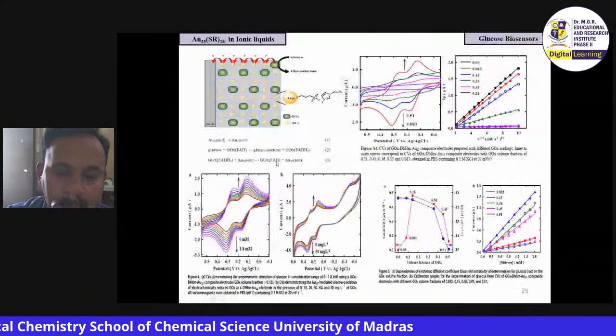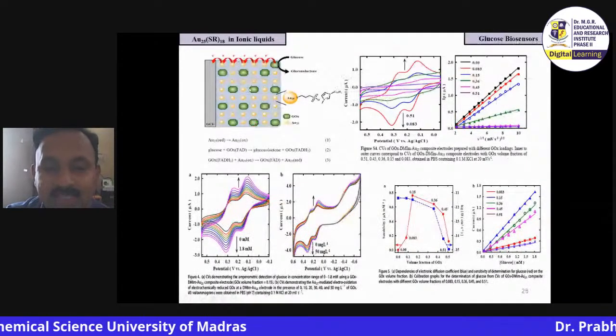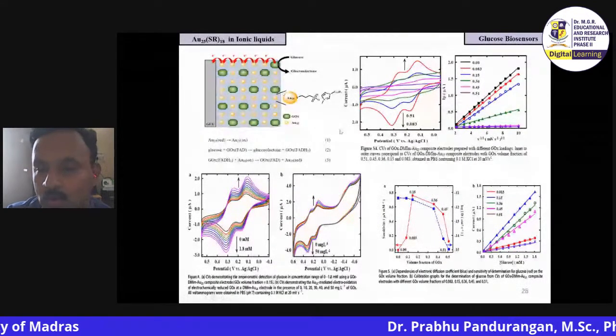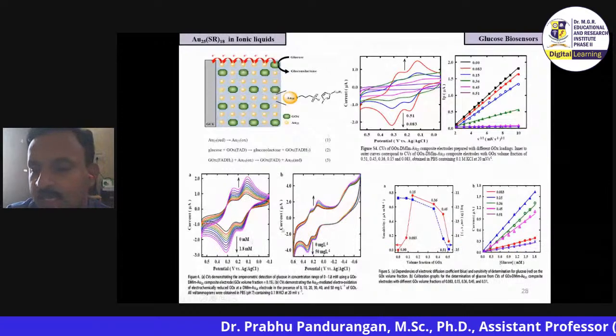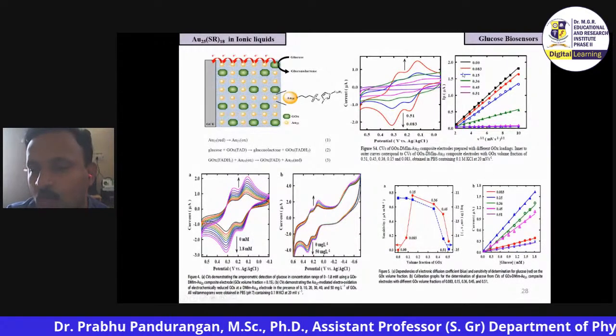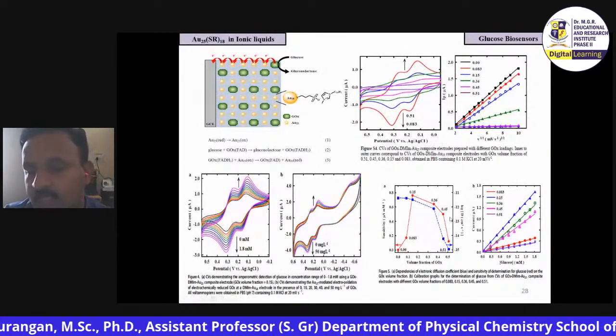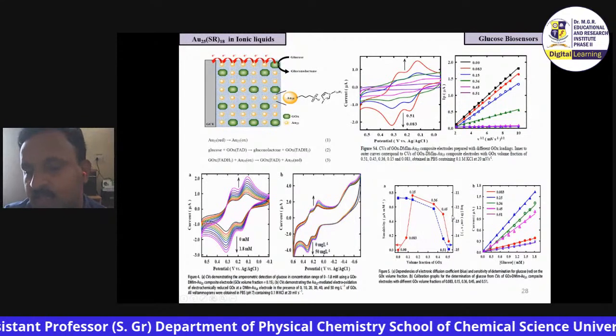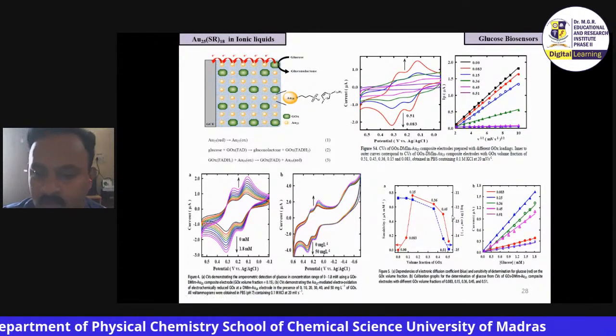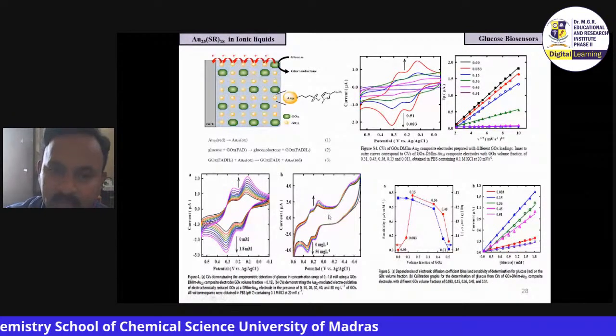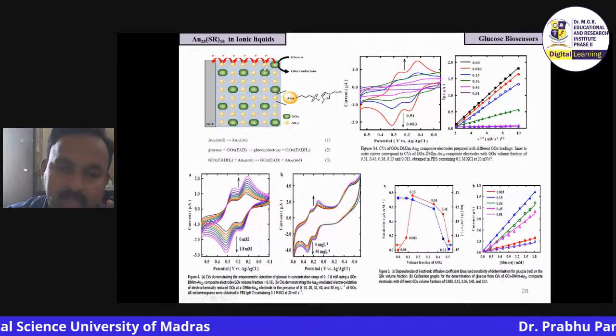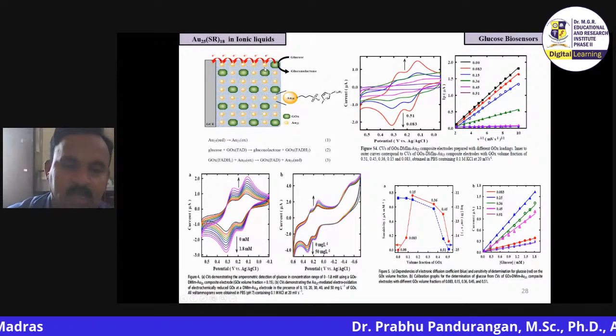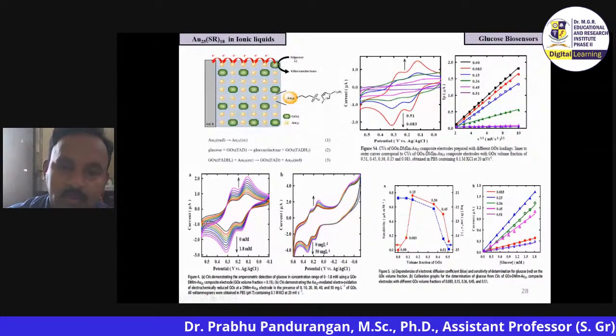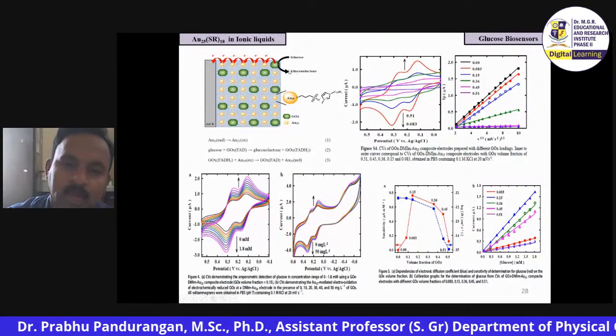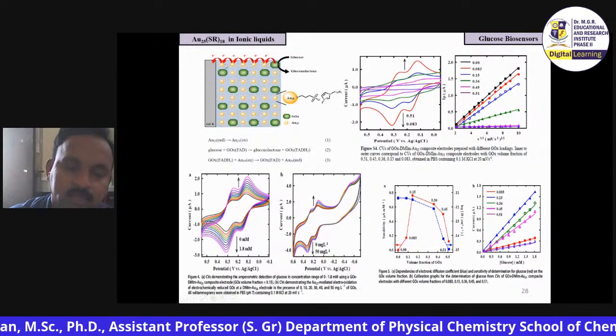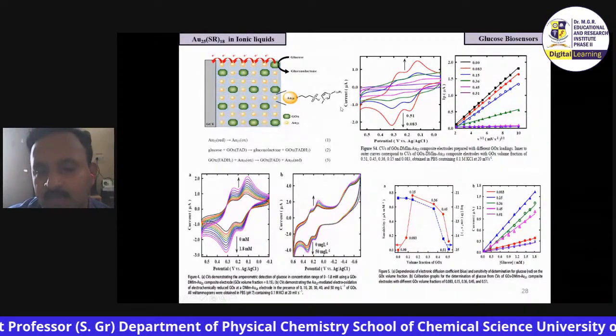You can see a paper in ACS Nano where they used enzymes with this gold 25 and were able to sense glucose. You can see the glucose can be sensed, and the calibration plots show how much you can tune both the enzyme as well as the gold 25 concentration in that matrix, and you are able to develop different calibration plots. But what I want to say is that gold 25 acts like an electron hopping process. It is acting as a mediator as well as a redox electron conductor. From enzymes, glucose is converted to gluconate, and this electron is received by gold 25. It is transferred to the electrode, and this is signaling as this response.